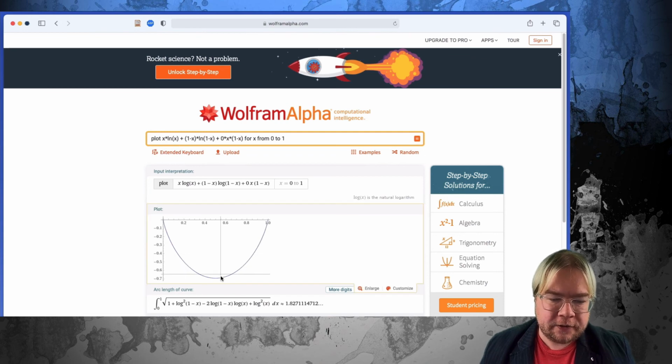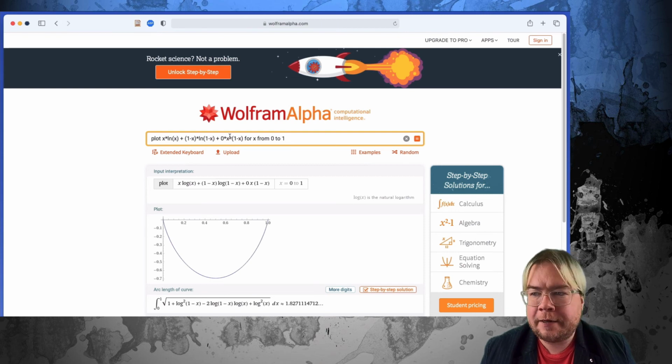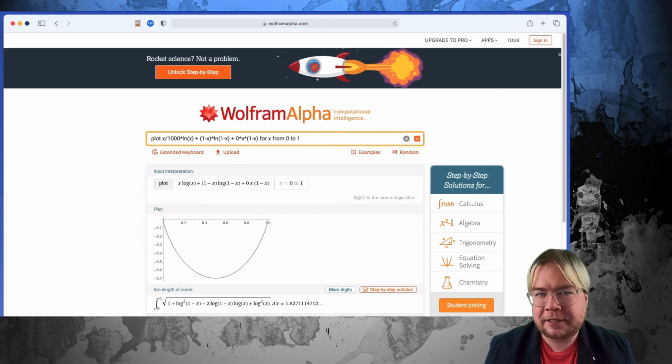Now pay attention to the scale here. So the scale, this is about minus 0.69 at the minimum of the function. Watch what happens if I divide by the degree of polymerization. Let's say that instead of looking at a regular solution, I'm going to look at a polymer solution. So NA will be really large. Let's say it's got a degree of polymerization of about 1,000. And the degree of polymerization of the solvent will still be 1.